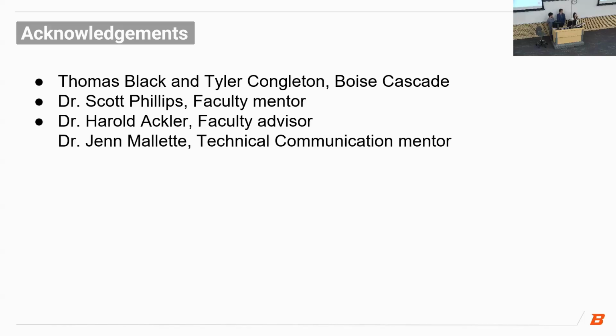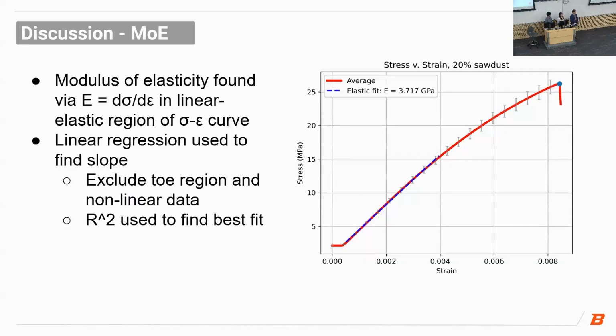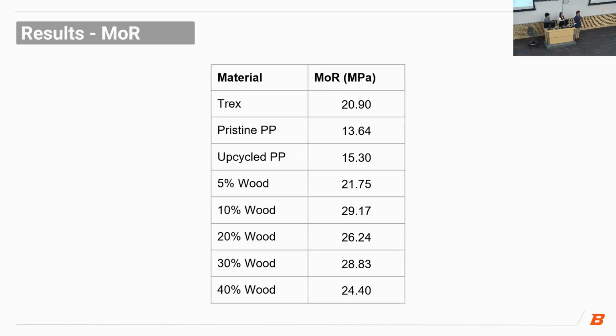Thanks. Great work. How did your test results on Trex compare to published data on Trex? So the results that we had on Trex compared to the published data seemed to be approximately the same. The MOR that we calculated was, I believe, within about 10% of the published value. But ultimately, the reason that we wanted to repeat these experiments rather than use published data is because we wanted to compare exactly the same samples of exactly the same shape and geometry on our setup. And so we feel like the Trex testing that we did is actually quite accurate in terms of its individual numbers, as that did not have any voids because we did not manufacture the Trex, obviously. But yeah, so within 10%.